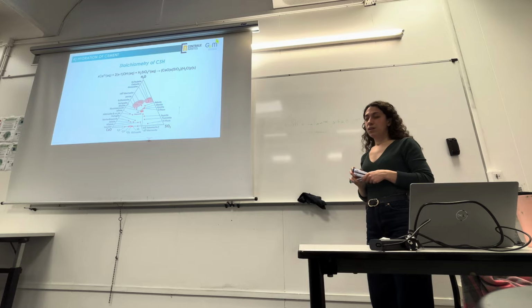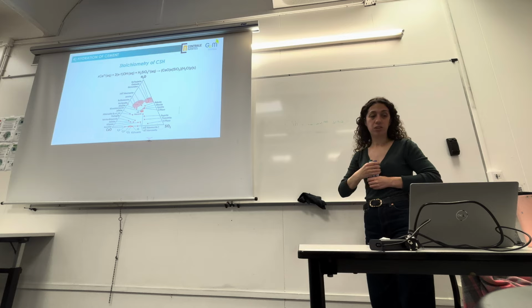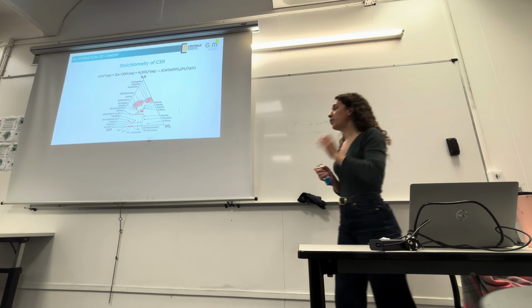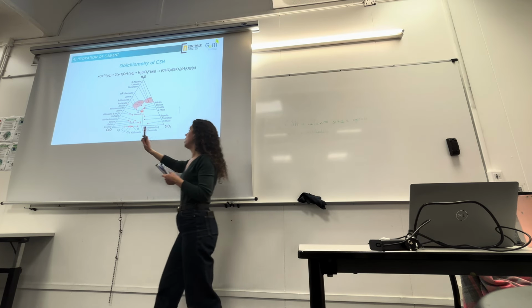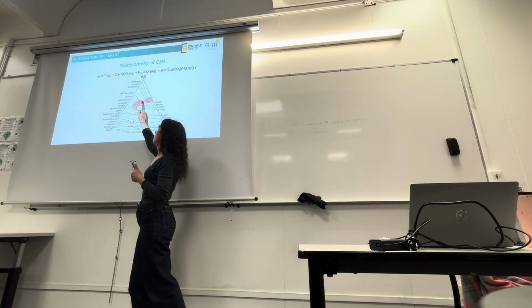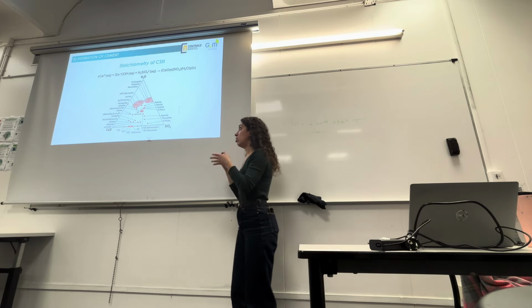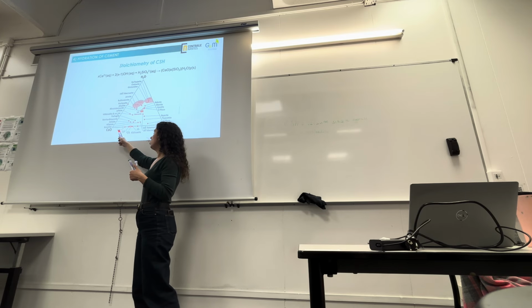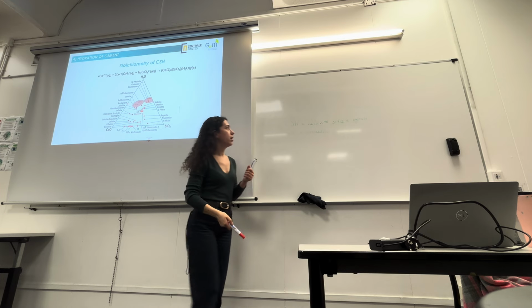I don't remember the word in French. Anyway, various preparations of minerals in the lab. So you mix calcium oxide, silicate, water, for example, and you get a CSH with a geometry close to CSH1 or CSH2. You can also get CSH in the lab by having pure C3S and hydrating C3S. But if you have pure C3S and hydrated C3S, as we've seen, you will get CSH but with portlandite.